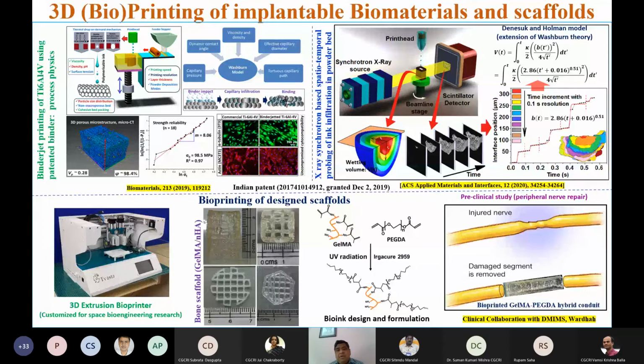Now, in terms of nerve regeneration, particularly peripheral nerve regeneration, we use a photopolymerizable cross-linked bioink, that is gelatin methacrylate. And the preclinical study is in progress in the rat model. So essentially, we put this hybrid conduit in the sciatic nerve when it is cut, and then we see how fast the nerve is regenerated at that place. And this is one of the works that I started at IIT Kanpur a long time back in 2006, and we still continue it in our group.